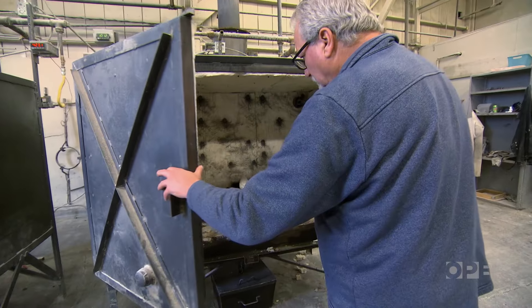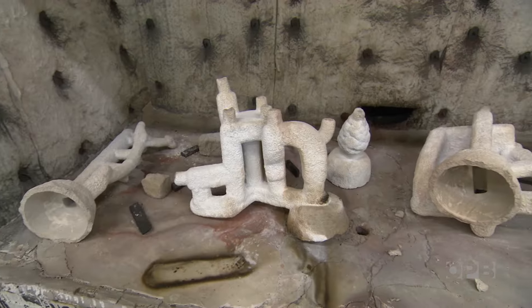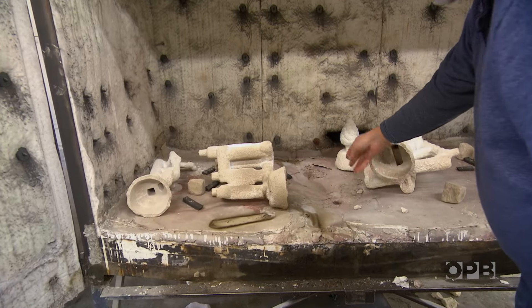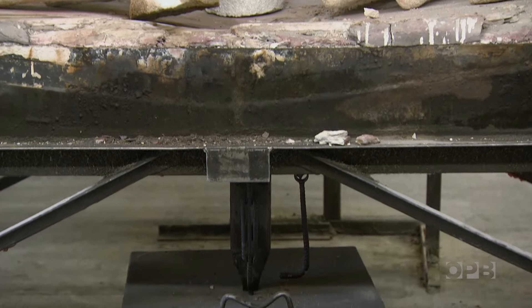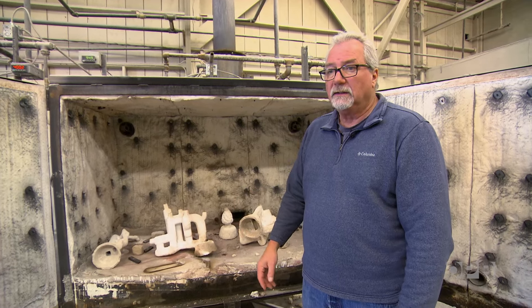After they've gone through the process of dipping and they're up to thickness, then we take them out and we burn the wax out of them in the kiln. In this burnout oven, the wax is lost or melts out of the heat-resistant shells. You can see how it's sloped to the bottom and there's a hole in the middle, and underneath there's a container to capture the wax. After we've burned them out, they'll be ready to go into the oven to be preheated and poured.